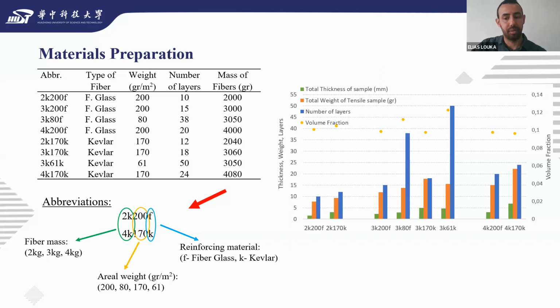About the graph, due to their different mass per unit area, we need a different number of layers to prepare the required fiber masses. As a result, each sample had different thickness and different mass when the epoxy was applied. So, the final samples were produced with different volume fractions. The different values of volume fraction are represented by the yellow bullets in the graph.